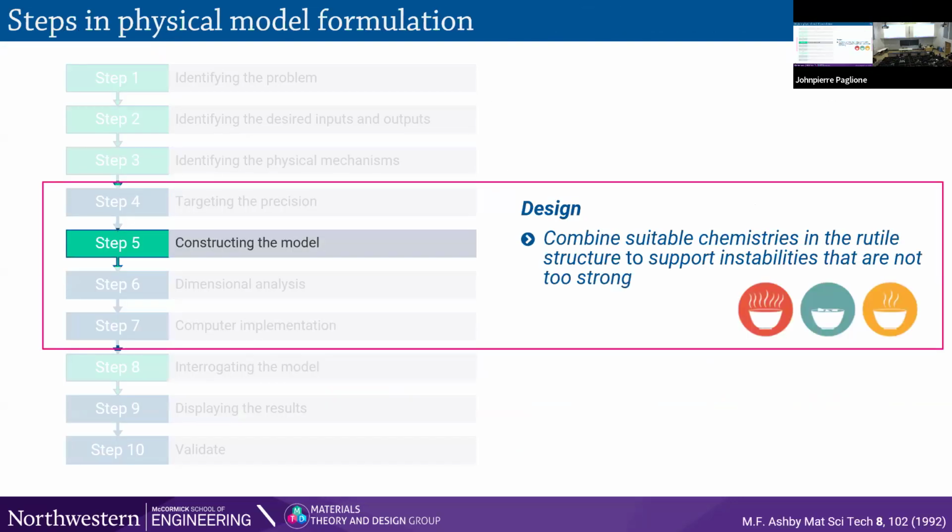So I'm trying to be mindful of time. Let's design the metal-insulator compound so then I can get to the altermagnetism. There's a subtlety which I didn't describe yet: when we choose chemistry, we're going to use the rutile structure because we know it can host a metal-insulator transition. Vanadium dioxide does that. But when we are trying to design for the transition, we're going from one state to another. That transition is driven by an instability. In this case, it's metal-metal bonding. Now when we design the material, if we choose chemistries which too strongly bias us in one direction, like the electrons always want to be delocalized, or we have too many of them, or the system always wants to have electrons localized, then we're going to be stuck in either the metallic state always or the insulating state always. So we won't have the transition. Phase transitions are this subtle balance of instabilities.